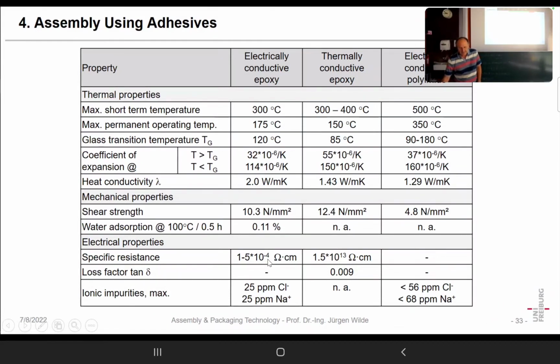Specific resistance is, let's say, maybe 10 times higher than for solder, but it's not really a problem. It's always sufficient. Loss factor for conductive material makes no sense. Another parameter is the ionic impurity. Here they give a maximum of 25 ppm chlorine.